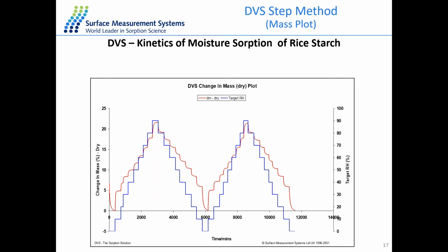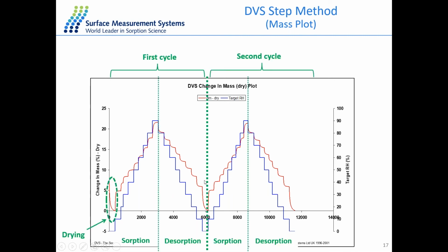So the same here, the blue line is the target partial pressure or relative humidity at each stage, and the red line is the change of mass for the rice starch sample. So at each stage, the sample reaches equilibrium and then jumps to the next stage automatically. And it's a two-cycle experiment with both sorption and desorption.